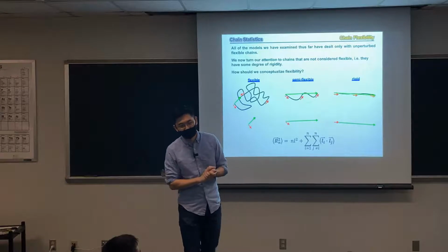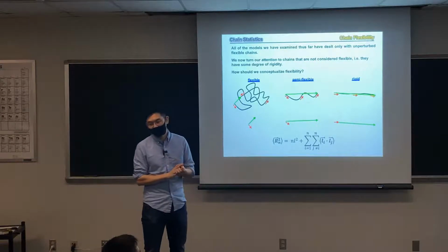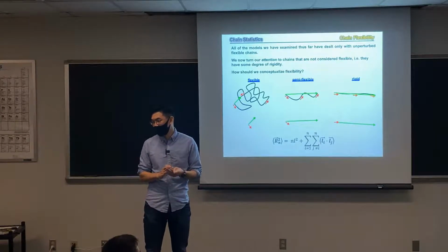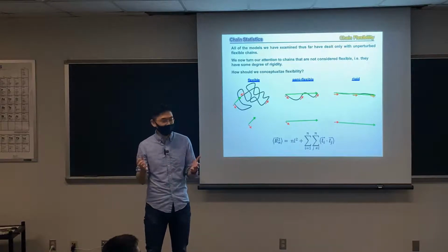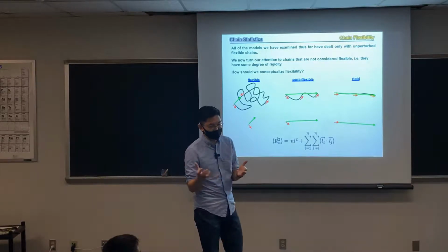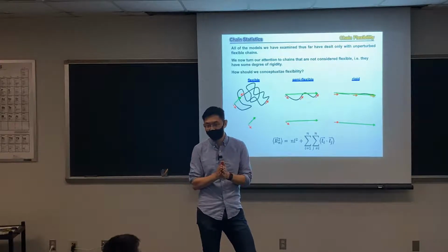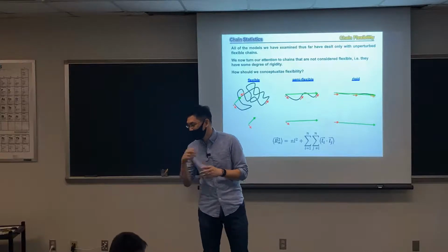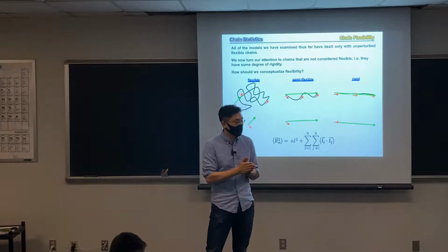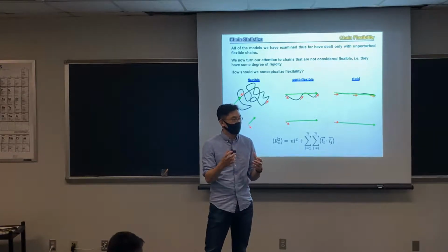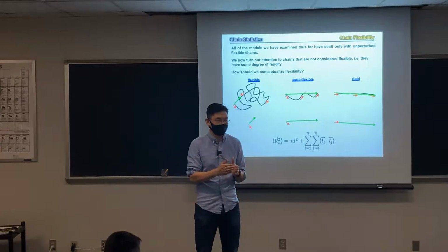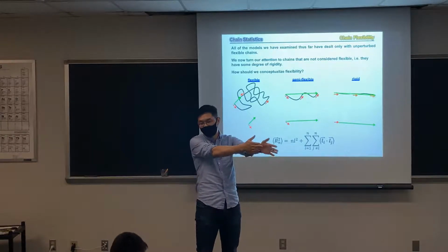It's typically on the order of 7 to 8 angstroms. If you compare 8 angstroms versus 20, 30 nanometers, your LC will be much bigger than LP. So your polymer behaves like a flexible coil. Okay? And that's typically the case for many commodity materials, polyethylene, polypropylene. They don't have any structures to limit your polymer to go in one direction.